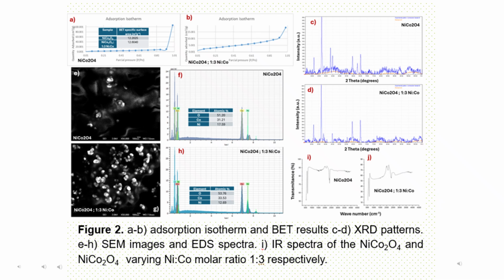The XRD patterns confirm the formation of a spinel in both samples. The characteristic reflections at 2 theta at 31, 37, 44, 59, and 60 were observed. The slight shifts in peak intensity are due to the different nickel cobalt molar ratio. This indicates maybe a smaller crystalline size and possible lattice distortions that could enhance their redox activity.